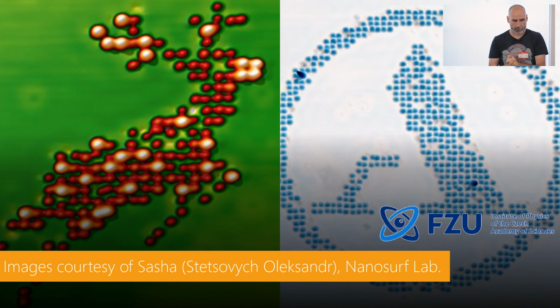But it's essentially a Jahn-Teller distortion, and what we're doing there is bringing the tip in above the down atom and flipping it up. So you can control it right down, to modify essentially conformation and bond angles right down at that level, but always dependent on the tip. So what we would love is a tip.